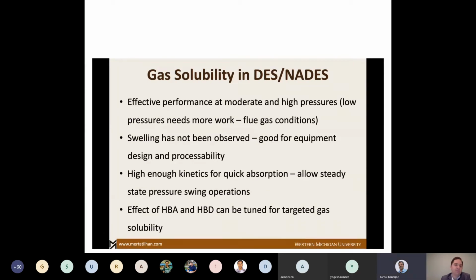Swelling has not been a problem, or hysteresis has not been a problem. This is good for equipment design and processability of these materials in the existing infrastructures. High enough kinetics for quick absorption. It is not the highest in comparison to the current state of the art, but this allows us steady state pressure removal based pressure swing operations. And we have observed from the molecular simulations that the effect of HBA and HBD can be tuned for the target gas solubility.